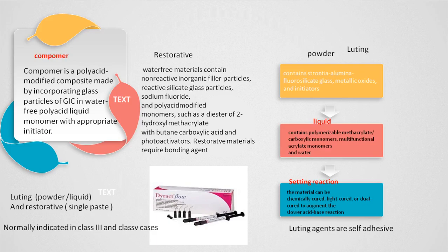Restorative consists of water-free inorganic fillers and reactive glass particles, which is nothing but a glass ionomer glass particle, and polyacid modified monomers like hydroxyethyl methacrylate in combination with carboxylic acid groups, and this also contains photoactivators. These do not have sufficient polycarboxylate groups, so they do not bind to the tooth and therefore require a separate bonding step. And luting agents, which consist of a powder and a liquid.